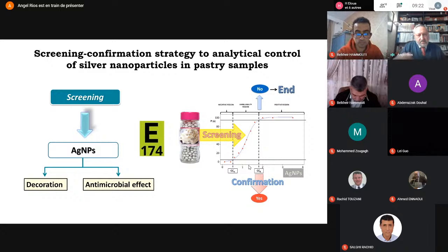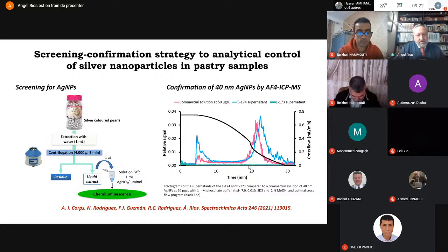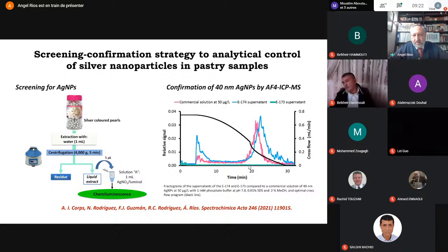So we have developed this screening method by combining a chemiluminescent check based on the reaction with luminol in order to check the presence of silver nanoparticles, because of the specific effect produced in this luminescent effect. And then we confirm the presence and the average size of the silver nanoparticles by using field flow asymmetric fractionation combined with ICP-MS, in order to confirm the presence of silver nanoparticles in the supernatant, for instance, and also the average size of these nanoparticles.